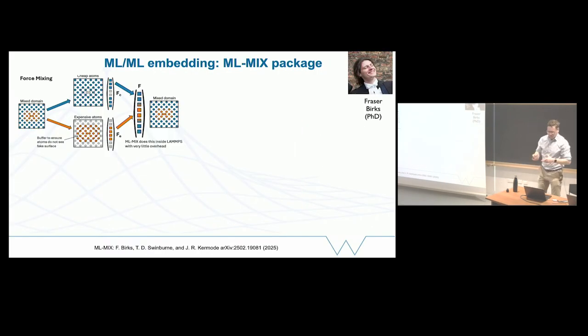Okay, good. So I want to show a few connections between the two halves of the talk. One is this idea of high and low precision. You can do just the same thing with machine learning potentials. And that turns out to be useful because these potentials are quite expensive, especially the accurate ones like I just showed. So we can use exactly the idea we had with DFT and with potentials, but instead with two potentials. We have some region where we need high accuracy, we have cheap atoms, we have expensive atoms, and we mix the two together exactly in this way.